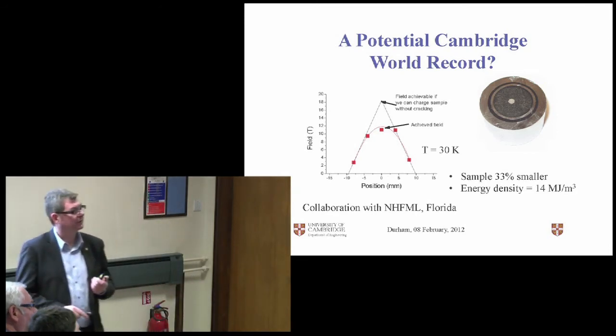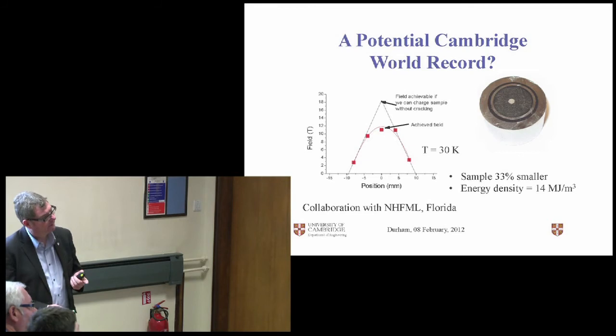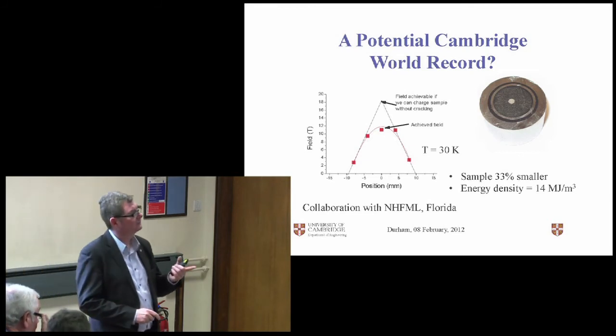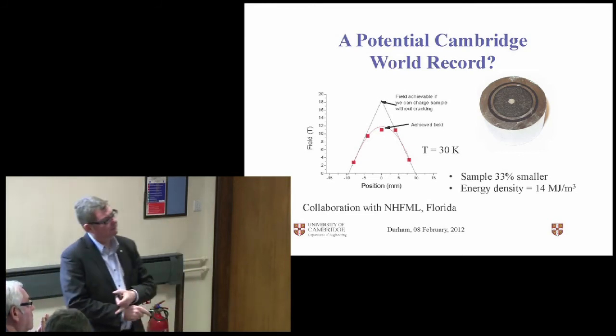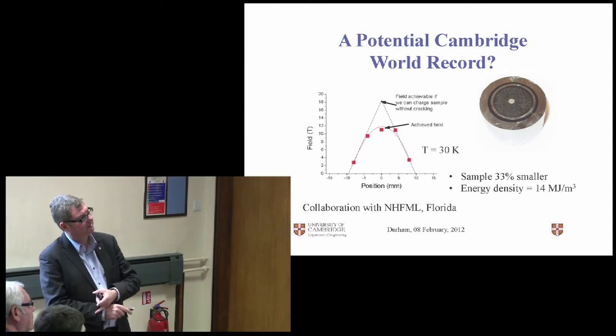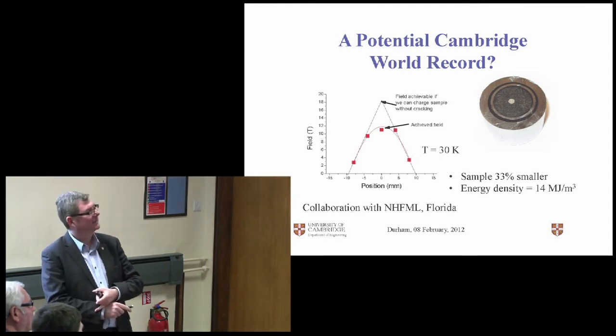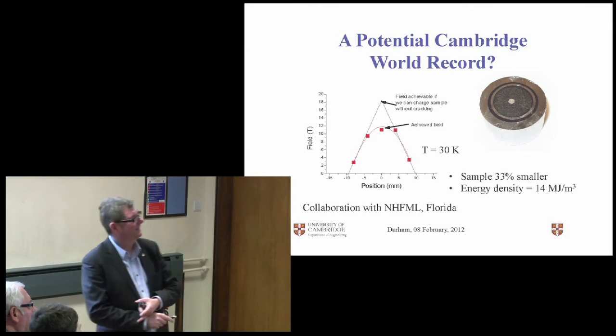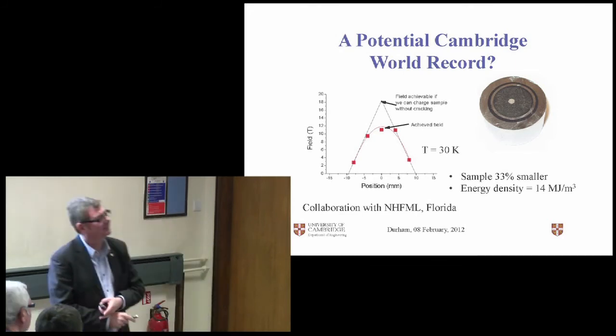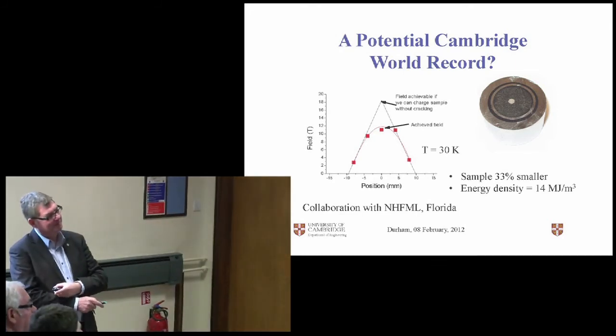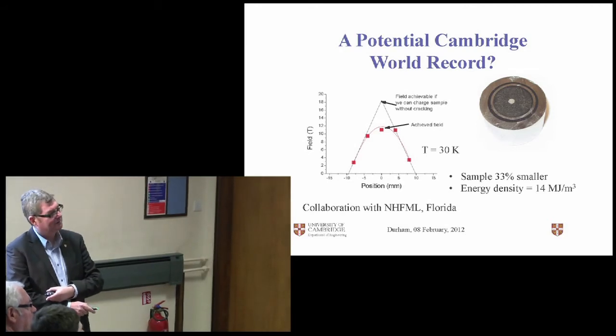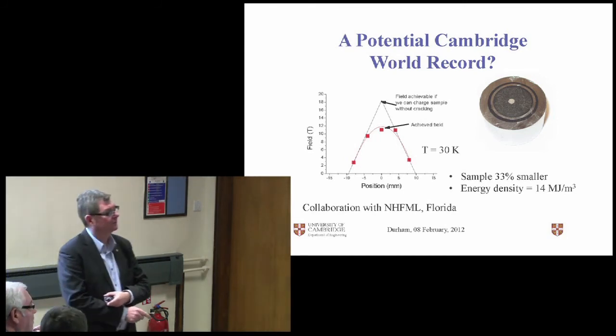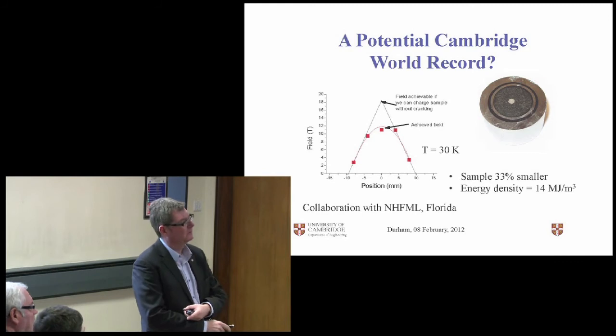And we're going to repeat the experiment in April. John Durrell is my postdoc, who's the world's biggest optimist, and he reckons if you extrapolate these curves here, spookily enough, you get to 17.8 Tesla. And this is his view rather than mine. But the whole point is, our temperature is slightly higher than Murakami's, and our sample's a lot smaller. So if it gets anywhere close to 18 Tesla, it will be a record field and a record energy density by some way.